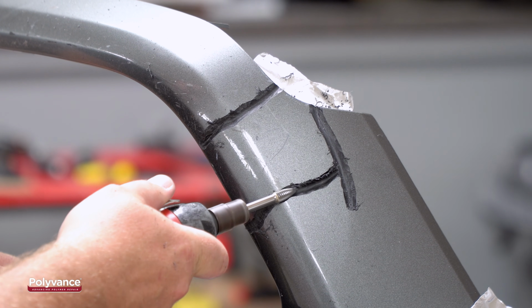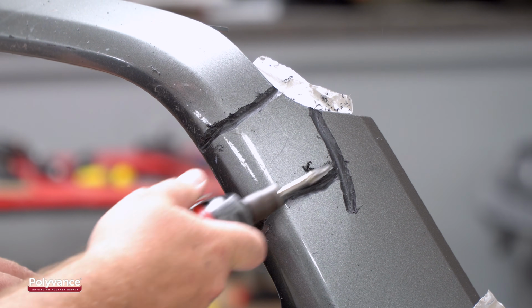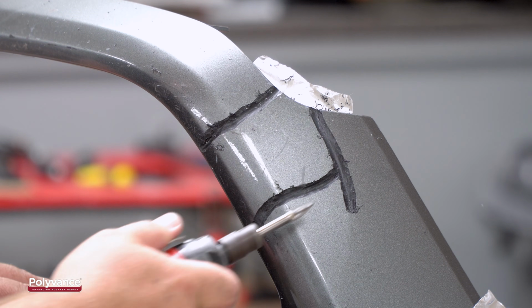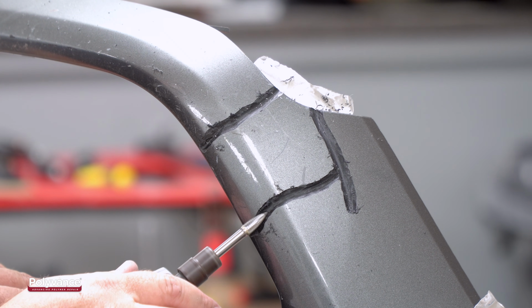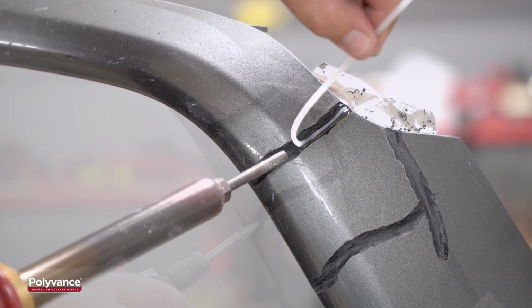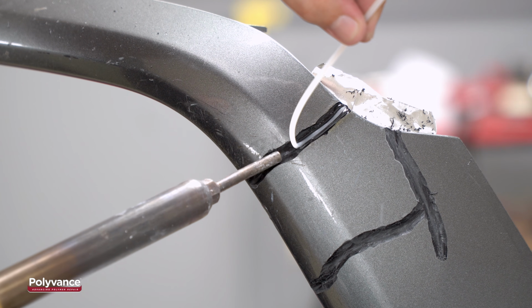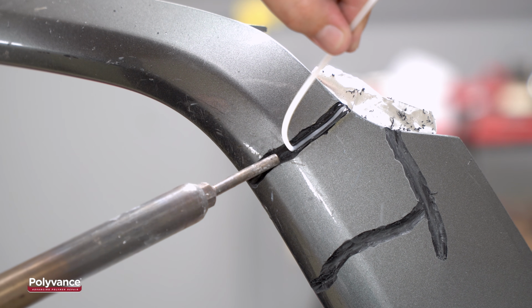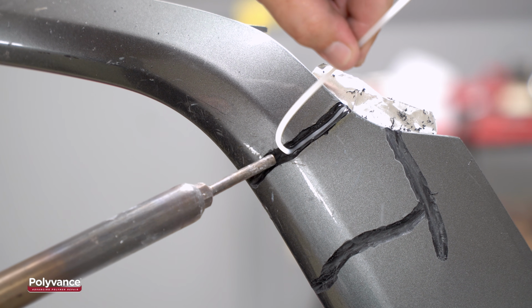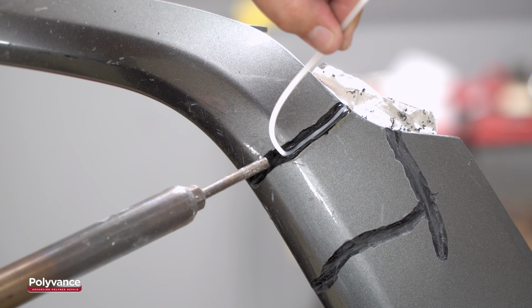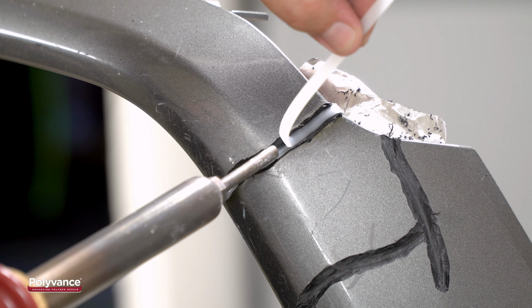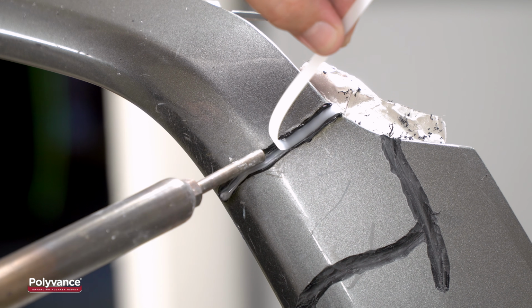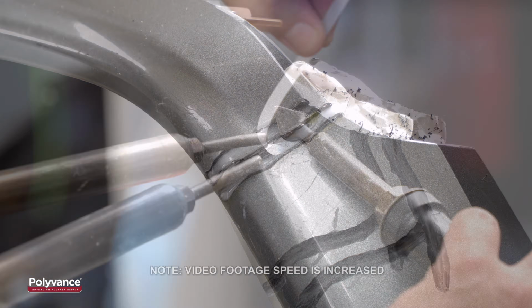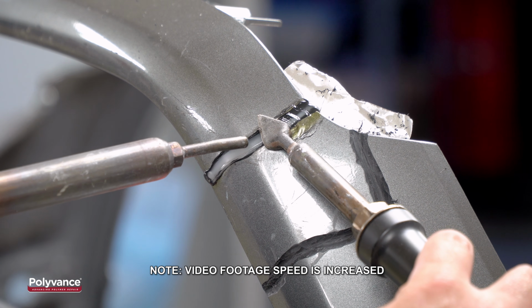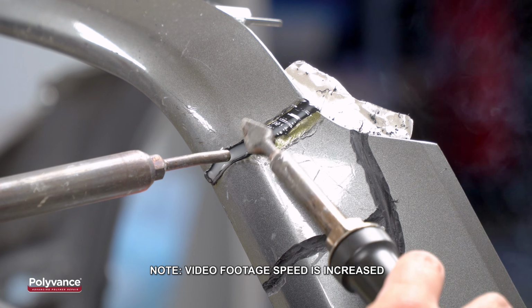Make a V-groove in the center of the crack, V-grooving at least halfway through the plastic. Once all the cracks are V-grooved, you can begin the welding process. Here, we used two different profiles of welding rod. First, we used Polyvance's round R02-01 welding rod to fill the crack, and then we capped it with the wider R02-07 welding ribbon. After capping the weld, we immediately smoothed with the airless plastic welder.